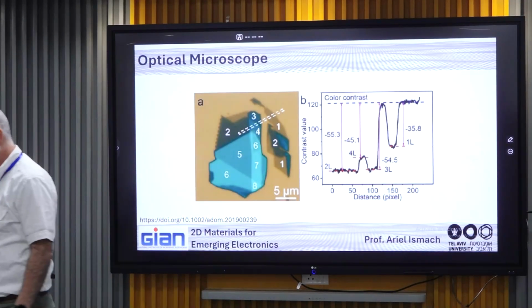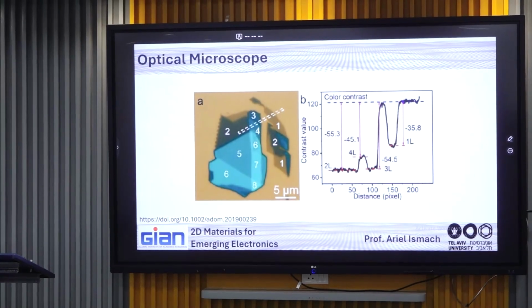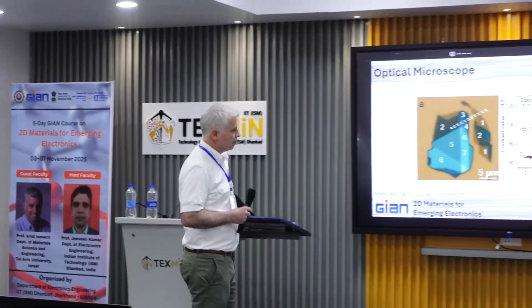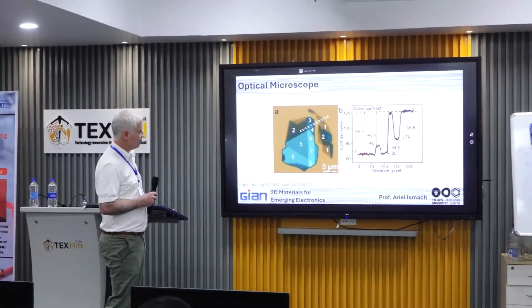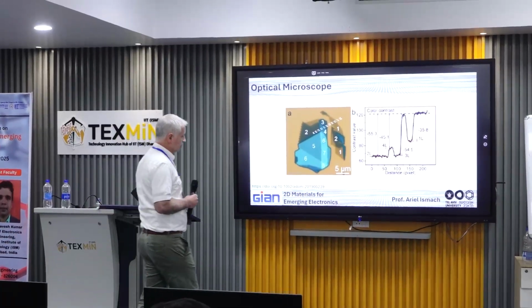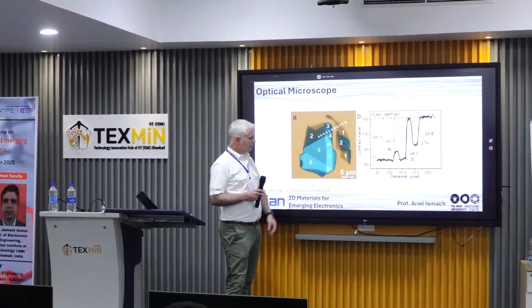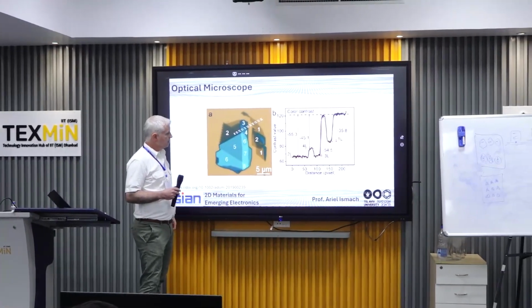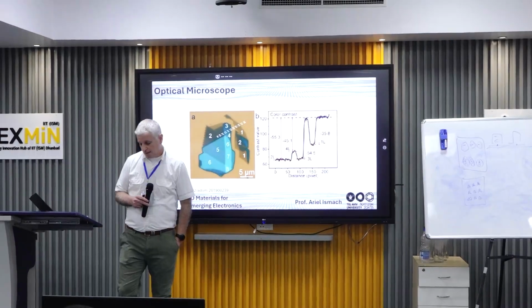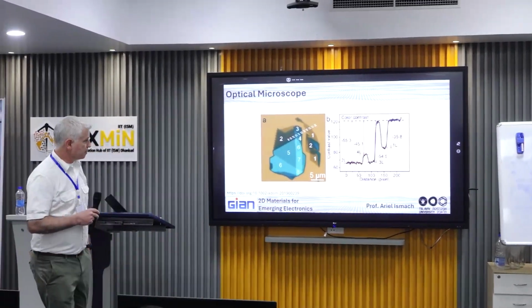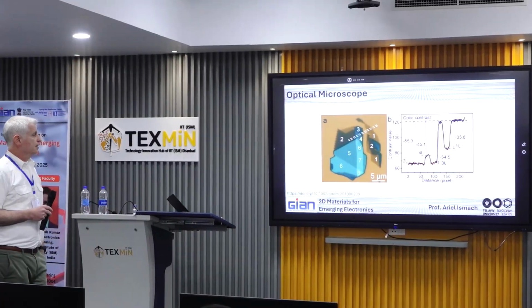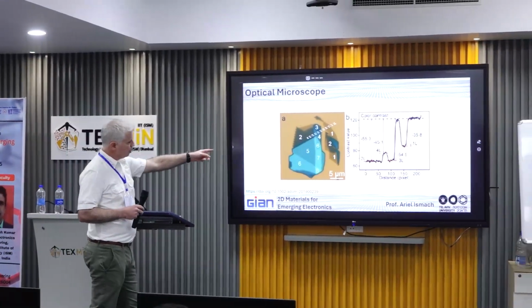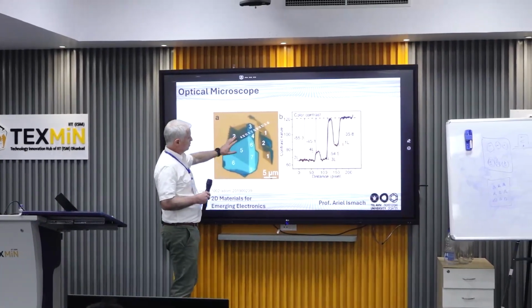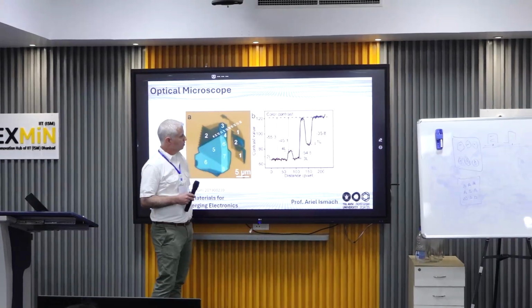And how many layers do you have? You can see that in the optical microscope by, for example, comparing the color contrast between the surface and the different layers. The thicker the material, the more reflective it becomes, and therefore you see it brighter. The thinner the material, it appears darker than the substrate. And therefore, if you take this image and plot the contrast, this is more or less what you will get.